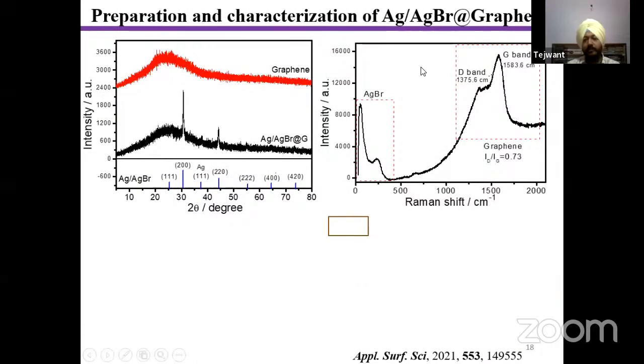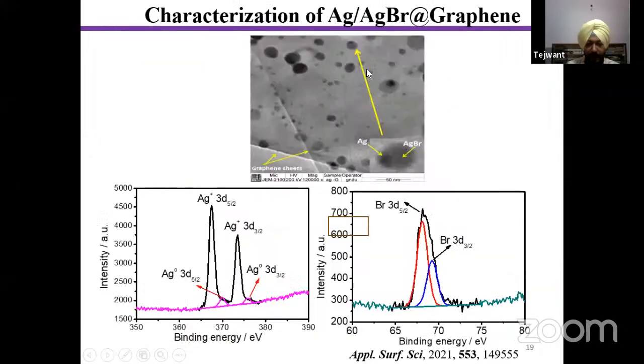This is again the Raman spectra, which shows both the presence of silver bromide nanoparticles as well as the presence of the D band, and the D band shows the presence of graphene. That has also been corroborated by transmission electron microscopy, where at the surface of graphene one can see the edges over there. We have put the yellow line. These are the edges of graphene. At the surface of graphene, one can see the silver bromide nanoparticles. However, the growth of silver is less when they are present at the surface of graphene. Further, the specificity of the presence of silver and silver bromide has been confirmed by XPS measurements.